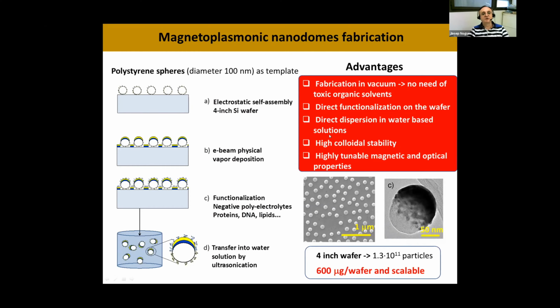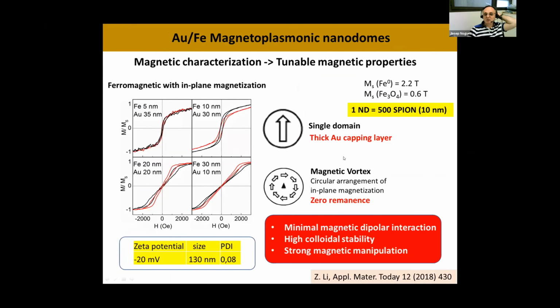So the advantage of this approach is we do the synthesis in vacuum, so we don't need any toxic organic solvents. It allows us to directly functionalize the nanoparticles while they're still on the wafer. It's very easy to disperse them in water, and they have a high colloidal stability, and they have tunable magnetic and optical properties. I'll show you now.